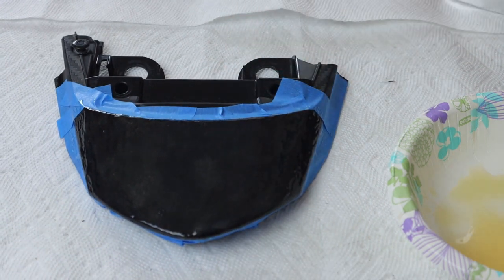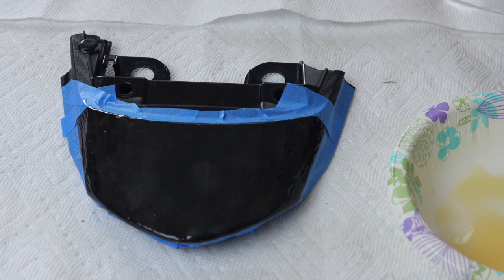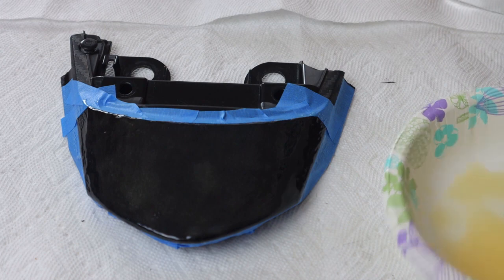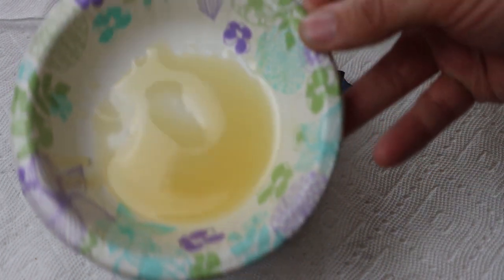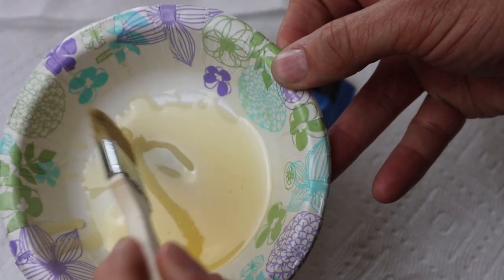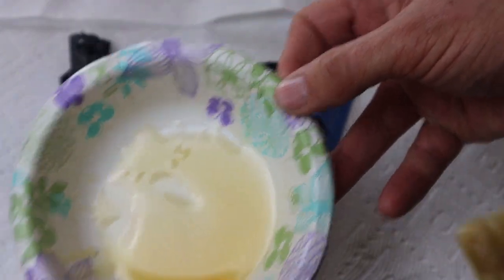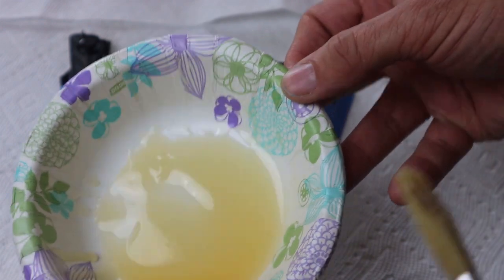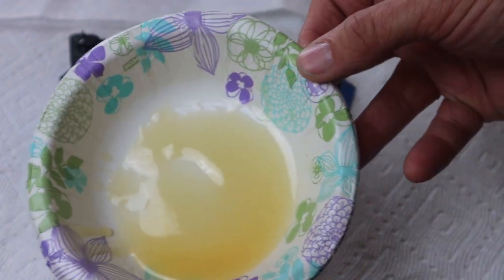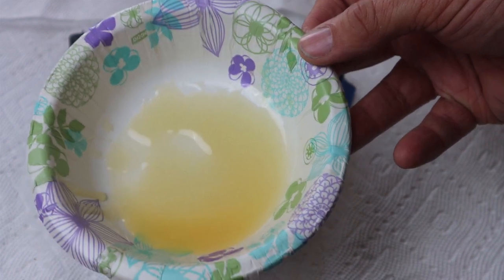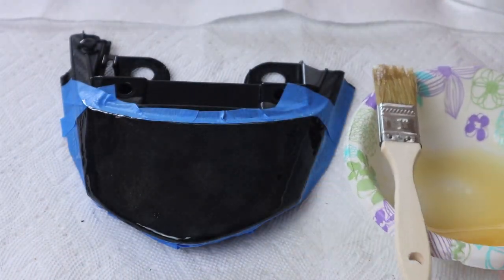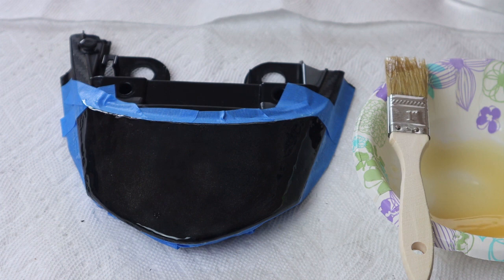Now we got the resin on the tail light assembly. We're now going to let this tack up. It should take approximately 3 hours, but every once in a while, keep your bowl of resin and come in and tap it with the brush. When you don't see any marks in your resin, then you can touch it with your finger. You want it just slightly tacky. So we're going to let this set now, and then we're going to come back after it tacks up, and put the carbon fiber ply down onto the tail light assembly.